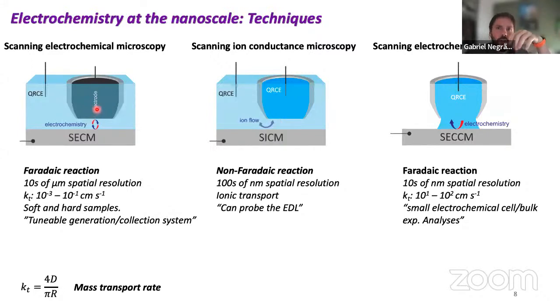But if I bring the electrode near a surface, features of that surface, for instance, let's imagine the surface is producing or consuming a species, will impact the electrode response, and that's how I can get information about the substrate as long as I'm close enough. The spatial resolution of this technique, I just point out, is tens of micrometers. Usually we can go to the nanometer scale, but it's quite challenging. So usually it's tens of micrometers.